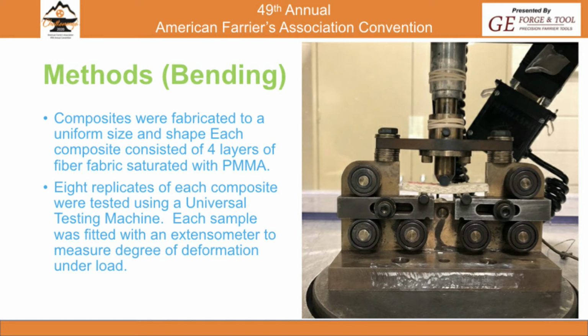So moving on from there, the next we tested was bend, similar thing. We made our little specimens. They're markedly smaller. They go into the same machine with a different jig, and it pushes down, and the extensometer is put up there. You'll see it on the back side with the rubber band, so it measures the rate of change within the Universal Testing Machine, or the Instron machine itself, and it's just tested in a 3-point bend. So again, 8 replicates of each, and all of these were made with polymethyl methacrylate. They were all rolled with 10 pounds of pressure 3 times, and they were all rolled with 4 layers of each repair material.